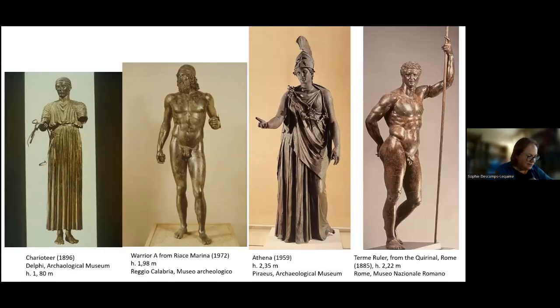So the indirect method of lost wax technique alone would not have been sufficient if not combined with another technique developed at the same time, the technique of flow fusion welding. This second technique was based on a high level of empirical know-how. Bronze makers were able to weld two sections together, head, arms, legs, by casting in between an alloy identical to their own, that is, melting at the same temperature, something that never happens today.